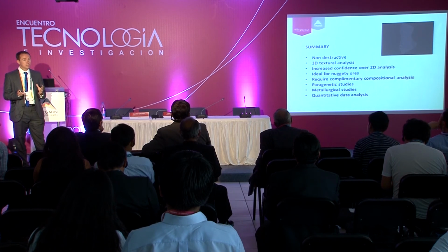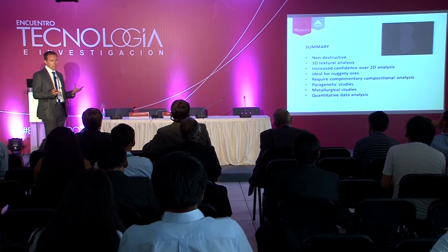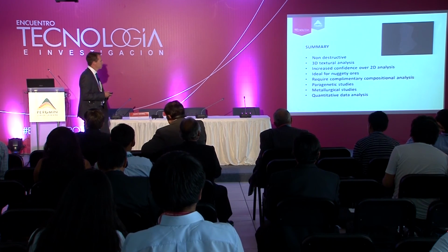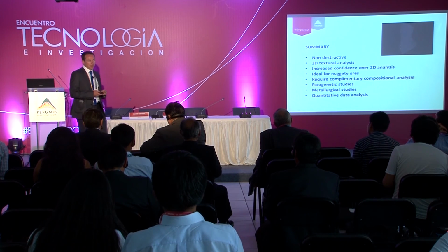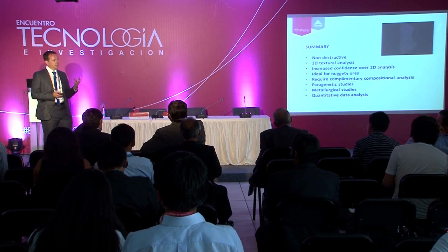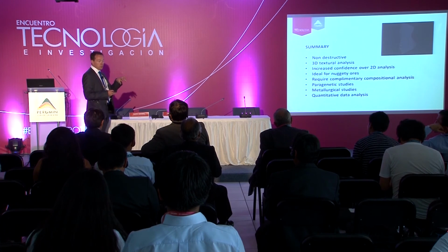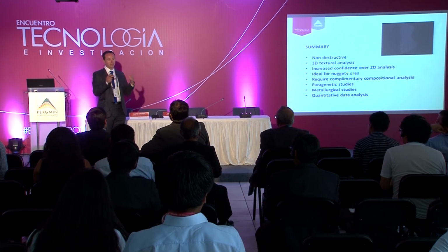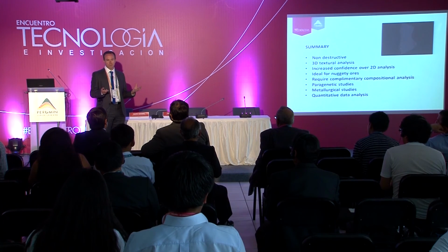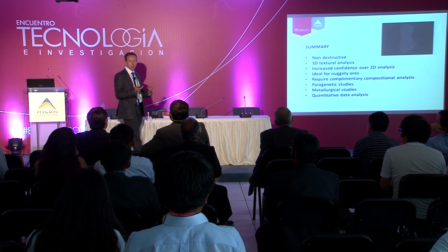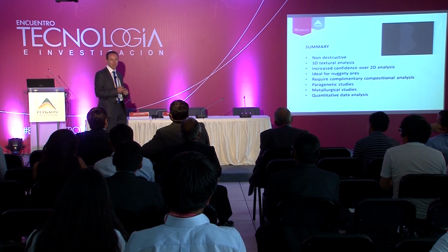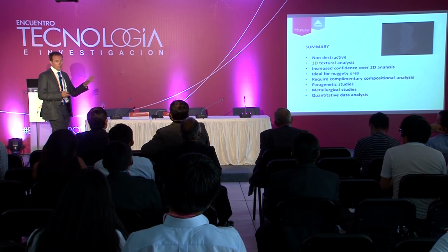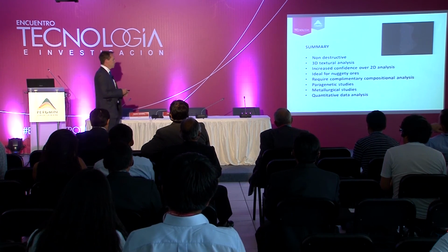If you don't have the density contrast, it won't work very well because that's what it is based on. So for example, if you're looking at a fossil which is preserved in calcite and the material that it's sat in is a limestone, there's not really any density contrast there, so this isn't a great technique for that. But where you've got ore minerals, pretty good.